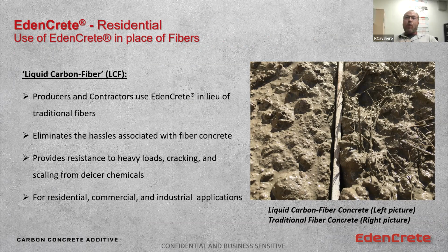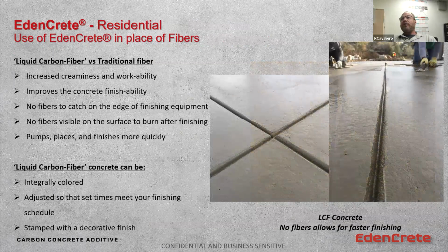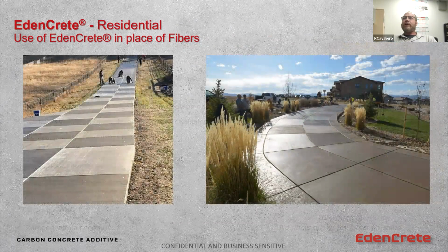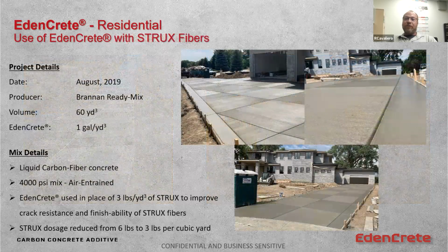or in lieu of with fibers. And we've gone out, we've developed a whole series of mixes, and those fibers lay down. They embed very well in the cream. You don't have to burn them off. You can finish your joints and you can cut down on fiber dosages, things that make the world of flat work finishing a better place, right?